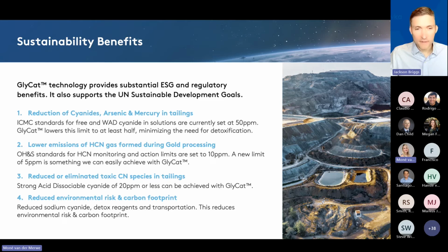And then in addition to WAD and free cyanide, we also reduce or eliminate other cyanide species like SAD cyanide. And lastly, reduced environmental risk and carbon footprint. So we're in the early days of doing a study that shows pretty interesting results around the reduction of a mine's carbon footprint that's achieved by reducing the amount of sodium cyanide that's consumed. And there can be some pretty substantial benefits on that front as well.